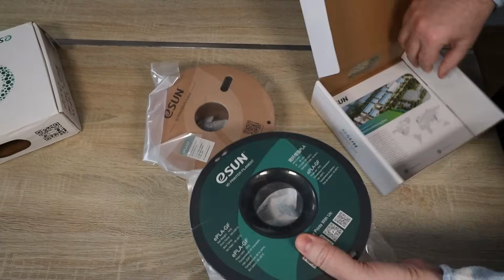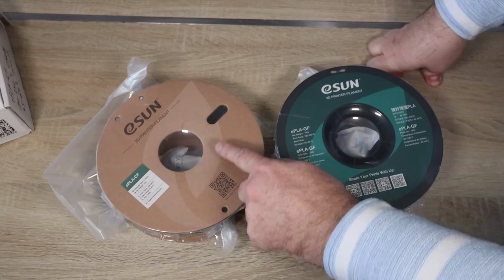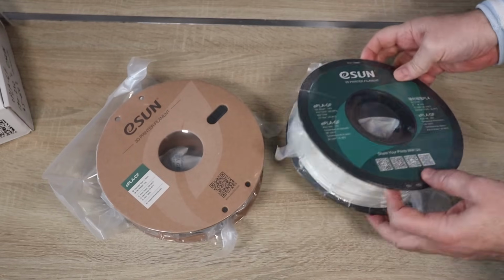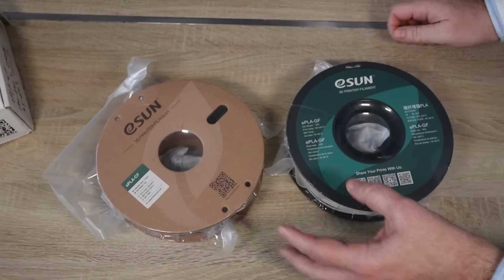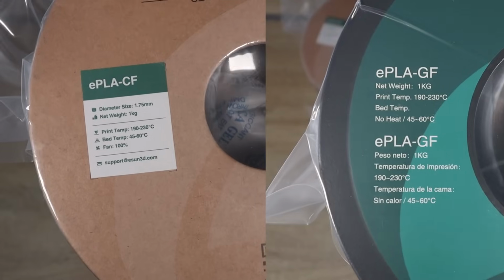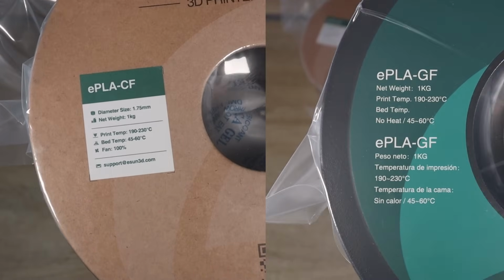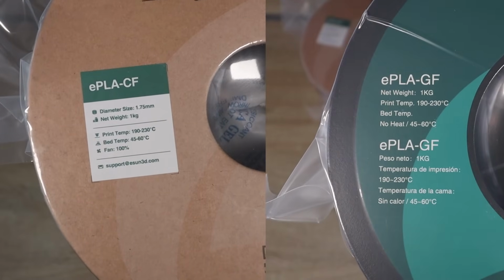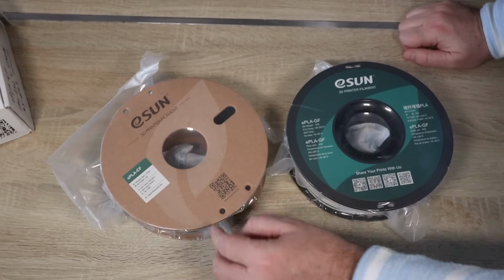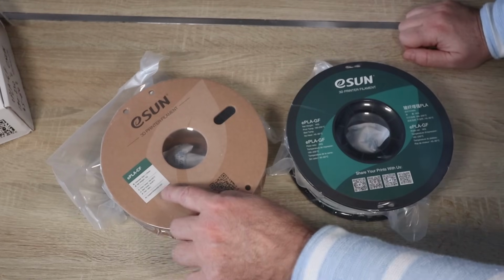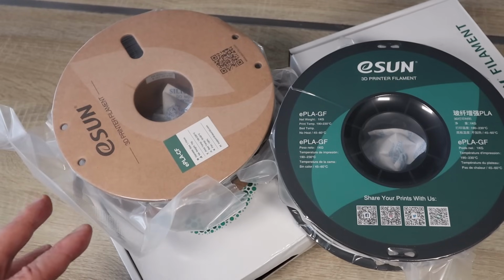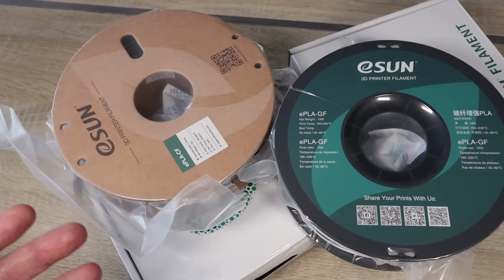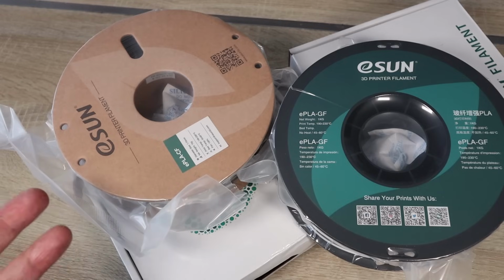Outside of the box I don't see too much information, only these stickers, so I will take them out. The carbon fiber version is black and the glass fiber is some kind of white. In both cases the print temperatures are between 190 and 230 degrees Celsius, bed temperature between 45 and 60 degrees Celsius, and the fan at maximum. Don't forget these are abrasive filaments and you need a hardened steel nozzle. According to eSun, the 0.4 mm size should be enough.